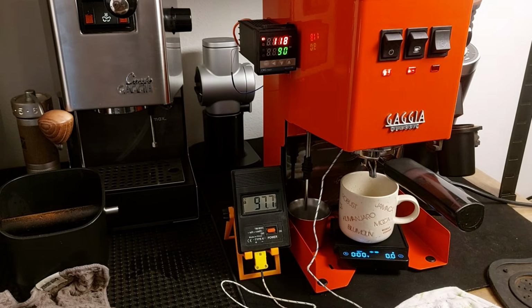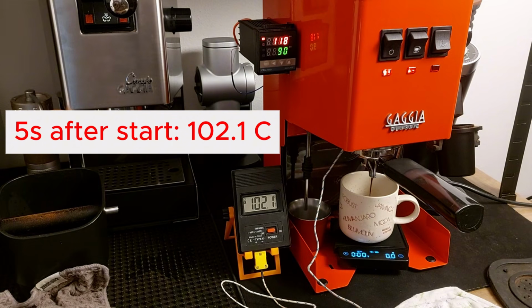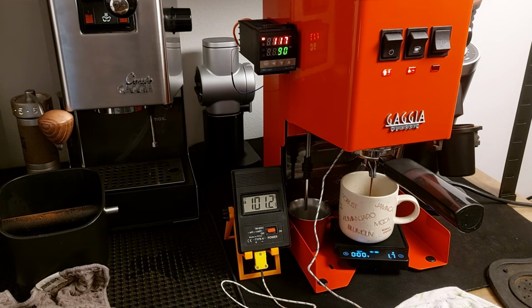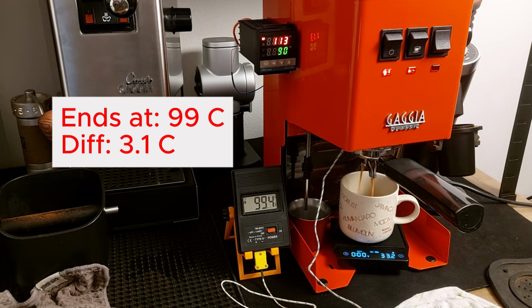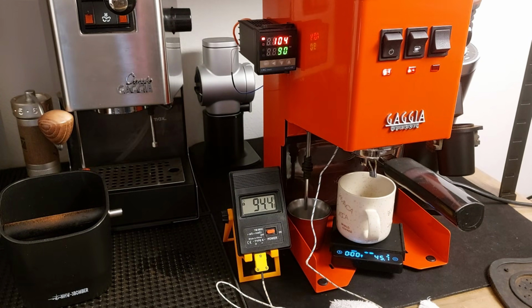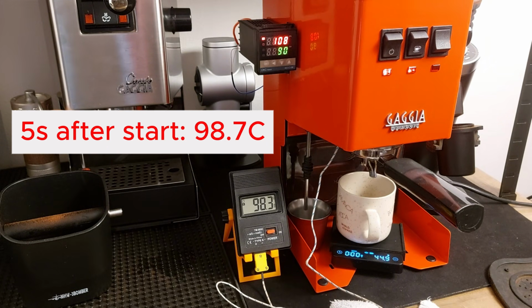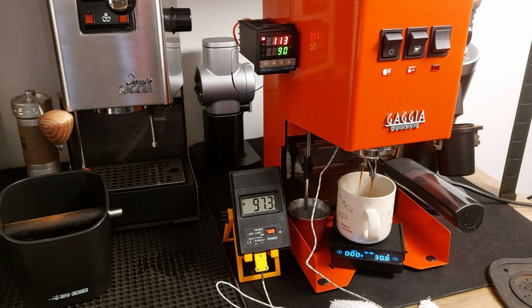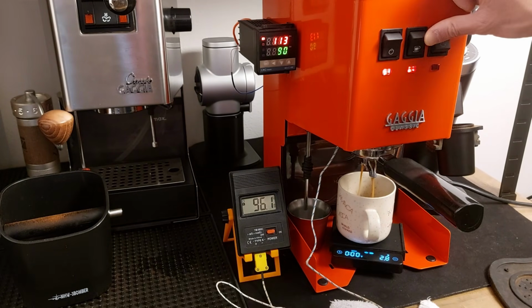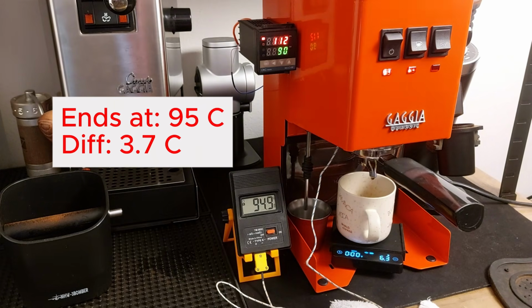Then I did the same at 118 degrees. So the temperature initially was at 102.1. It decreased to 99, so 3.1 degrees difference. Very stable as well, but super hot. Maybe if you have a fermented coffee, you may give it a go, but I think it's too hot. Then the third test was when the light goes on, and it started at 98.7, decreased to 95 degrees, so 3.7 degrees difference between maximum and minimum, which is still excellent.